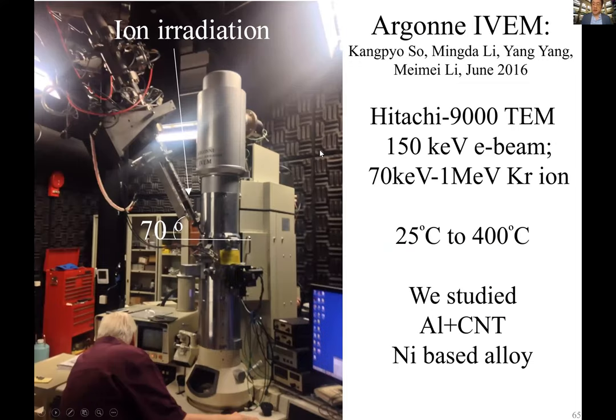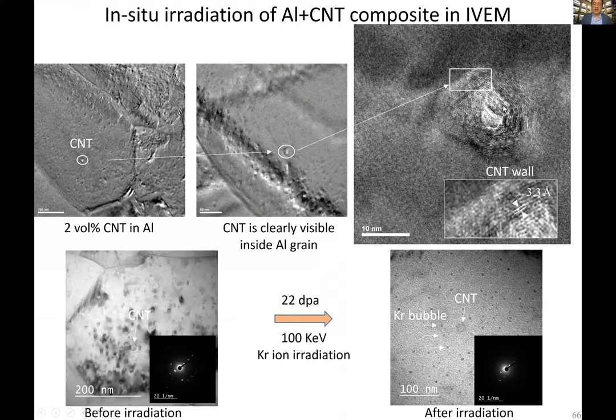We've also done in situ TEM observations, mainly in collaboration with Argonne National Lab, where this is the ion beam that's coming at a sample, and this is the electron observation column. We can clearly see multiple carbon nanotubes, where the spacing is 3.3 angstrom. And the key thing is this is not on the grain boundary. This is in the interior of a grain, so we have this intragranular dispersion. Then with the krypton ion radiation, we form these bubbles, and you can see the radiation defects. The resolution is not so good, but we see this kind of radiation defects get absorbed into the carbon nanotube.